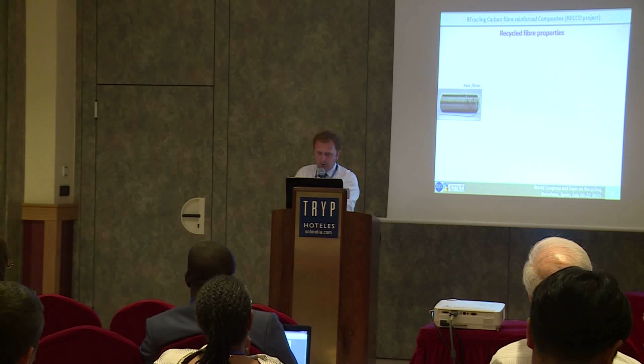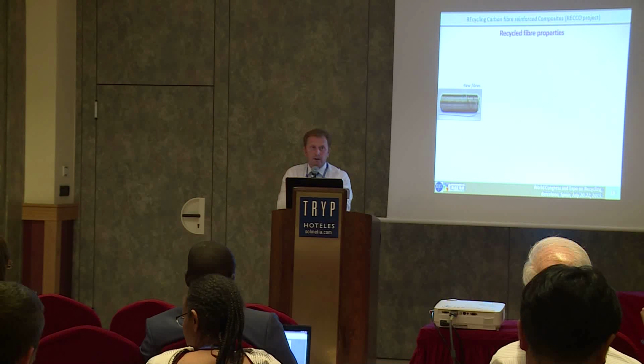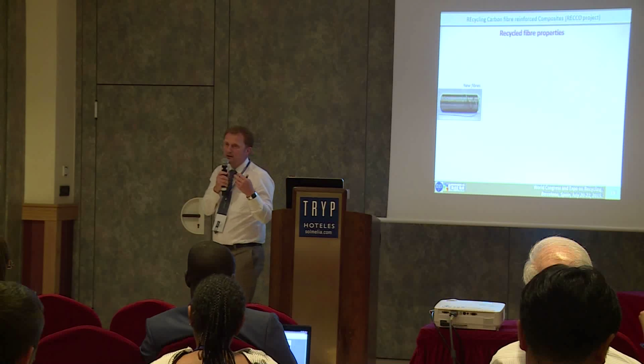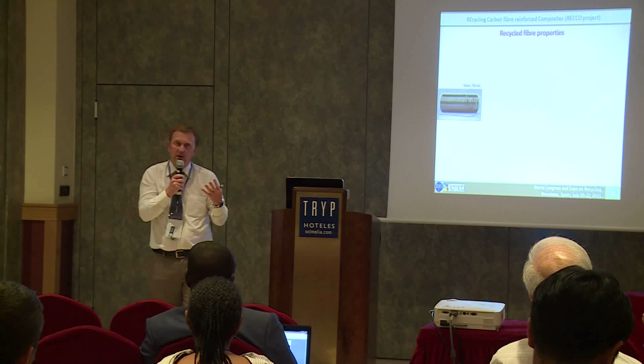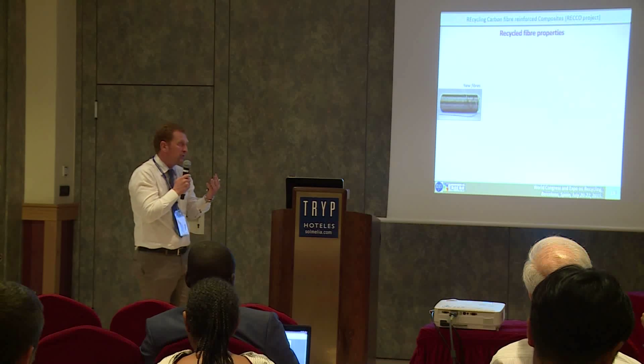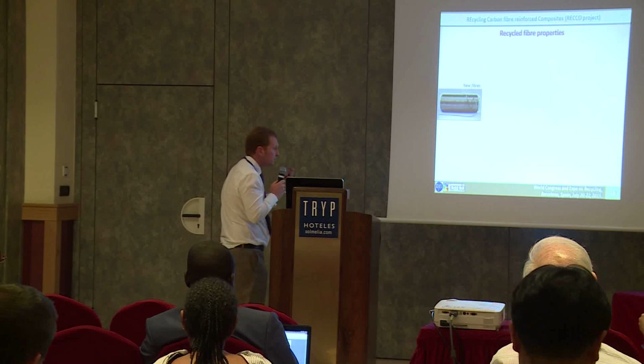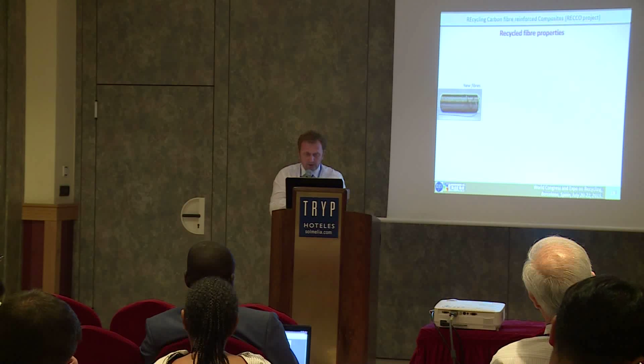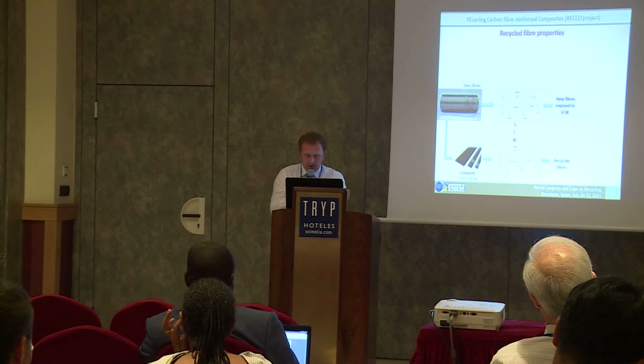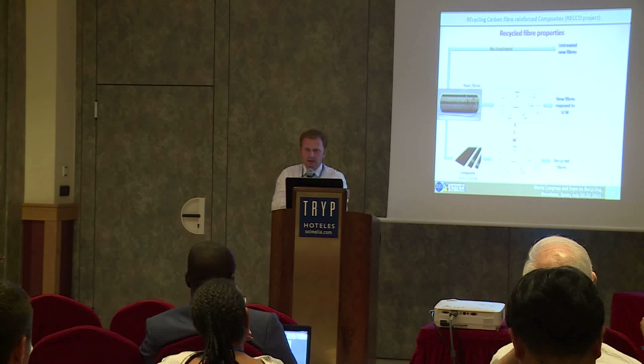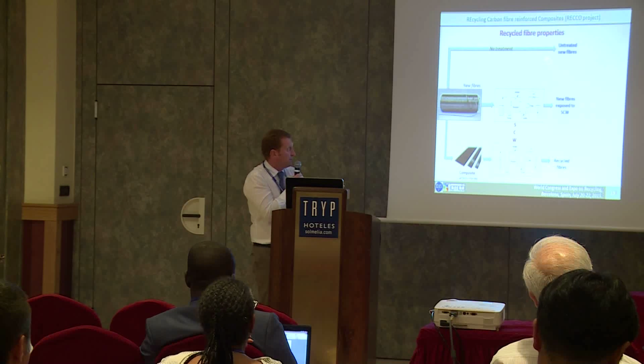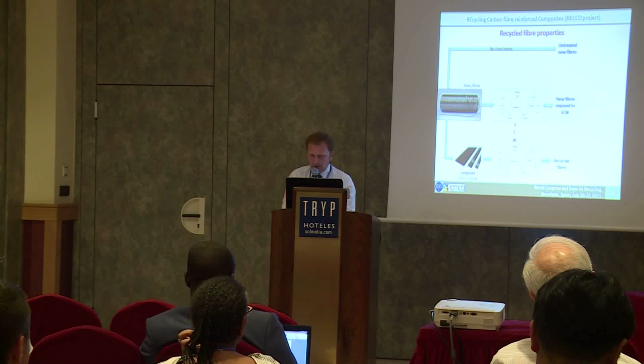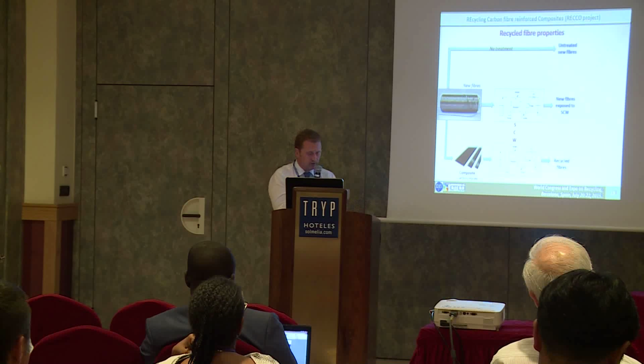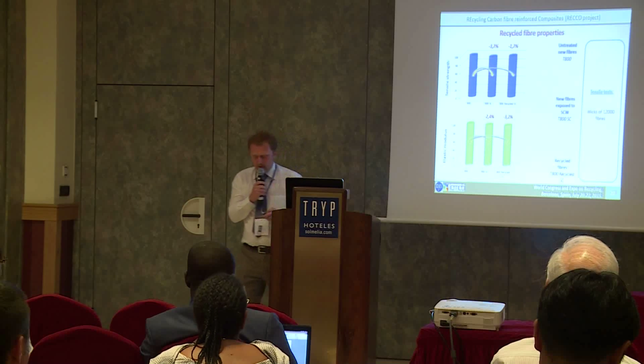Some colleagues from the mechanics department in Bordeaux made some important tests because one of the motivations of this work, as I told you, was that we knew the chemistry was okay, but we needed to prove that there was not a big effect of the treatment on the mechanical properties of the fiber. So they did three kinds of experiments. Of course, the reference, new fibers exposed to supercritical water treatment, and the recycled fibers. So here are the results.